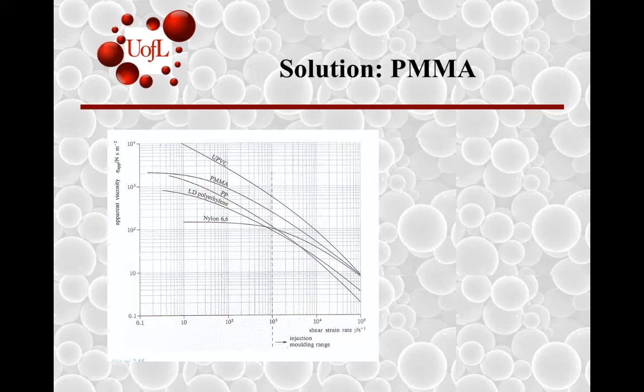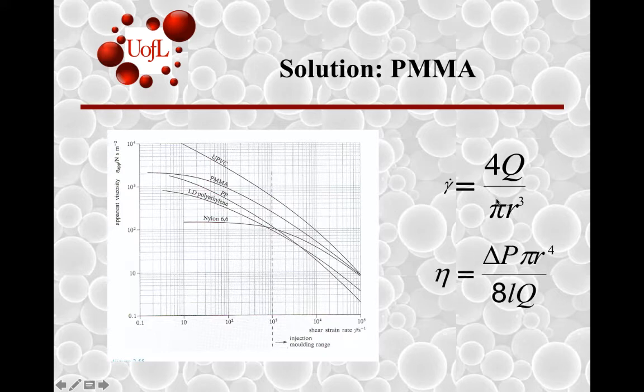To take the same solution for PMMA, we have as data viscosity as a function of shear rate. In order to find the viscosity, which is not given, it depends upon the shear rate. The shear rate can be computed from Q and R. Once you know the shear rate, you can from this map for PMMA decide what is the viscosity in this log plot. Once you estimate the viscosity, then you know Q, L and R and you can estimate delta P. You get it to be 24 megapascals, compared to 8 kilopascals. About 4 orders of magnitude difference in terms of the delta P that is required.